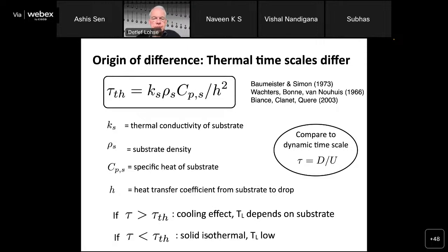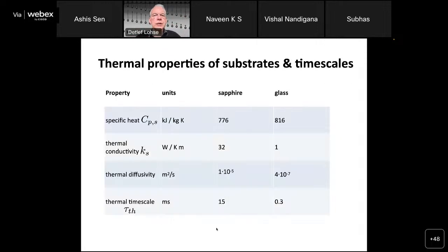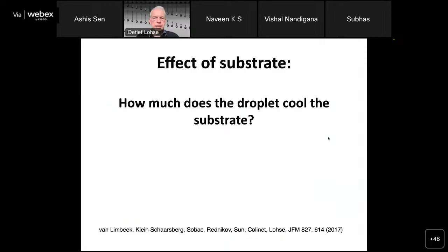So then the solid is isothermal, and enough energy is always in the solid to keep it at constant temperature. When you now look into the numbers of sapphire versus glass, you see that there's a huge difference in thermal conductivity, sapphire versus glass, a factor of 32, resulting in a huge difference in thermal diffusivity, and therefore resulting in a huge difference in the thermal timescales here. So the thermal timescale for sapphire is 15 milliseconds, and for glass it's only 0.3. And when you now compare it with the impact timescale, which in our case is about 1 millisecond, you see that you are in two different regimes here. So at sapphire, you have, so to say, a thermally perfect impact, whereas glass, you don't. Therefore, you need higher temperatures of the substrate to achieve the Leidenfrost state.